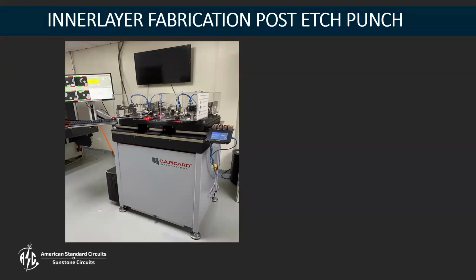There's targets on every layer, and it goes into this machine, and it looks for the true center as best as possible of both sides, all 4 edges of that panel. So you're talking 8 different points that it's looking at, trying to get the best true center of those 8 points, and then punches in our tooling holes that will be used during lamination. Usually the registration tolerance on this type of equipment is pretty tight, and we're able to get pretty good layer to layer registration.